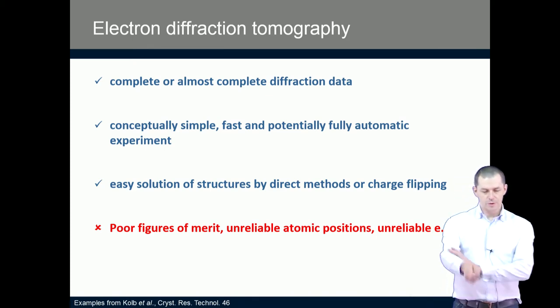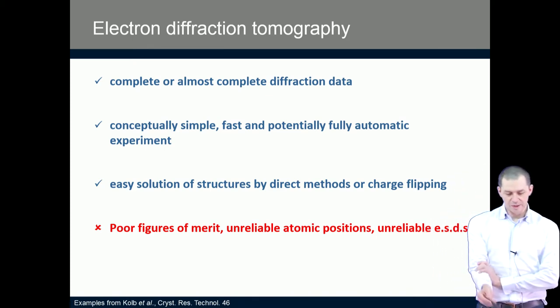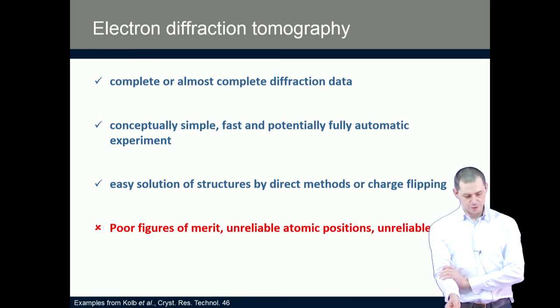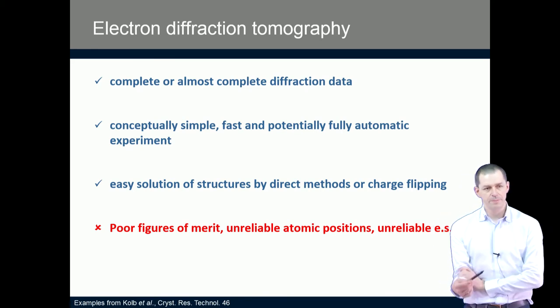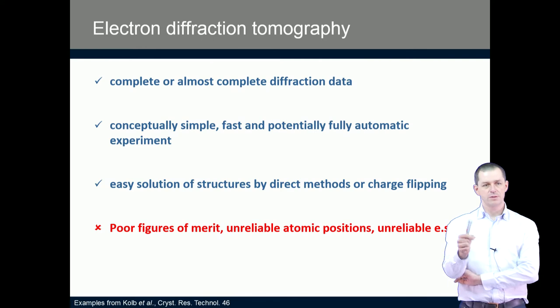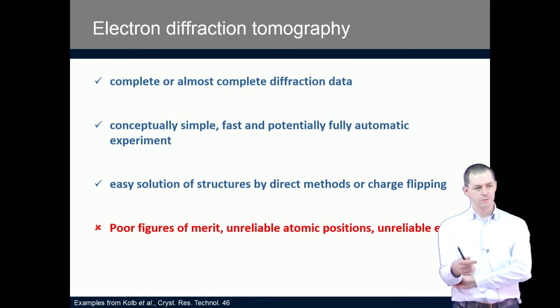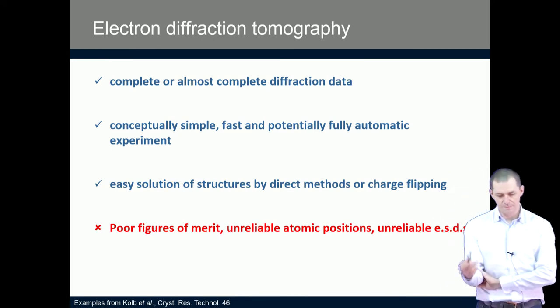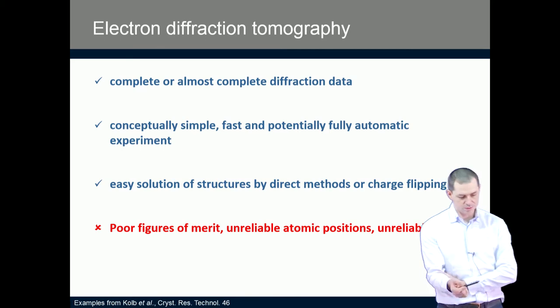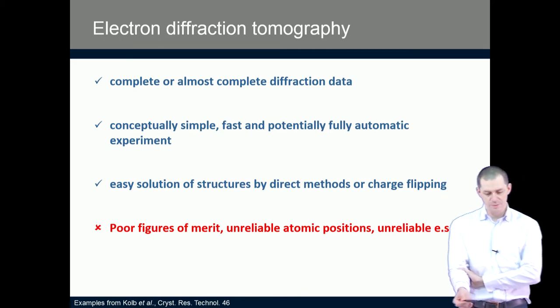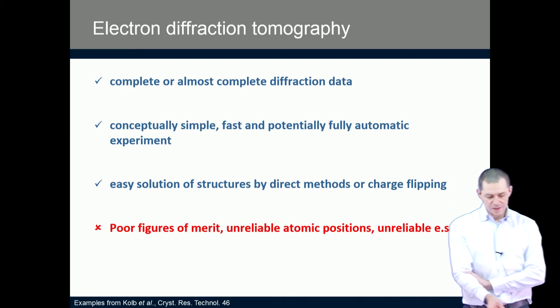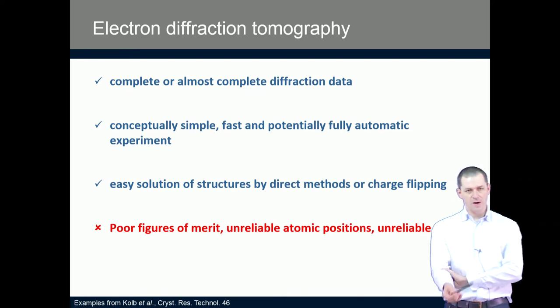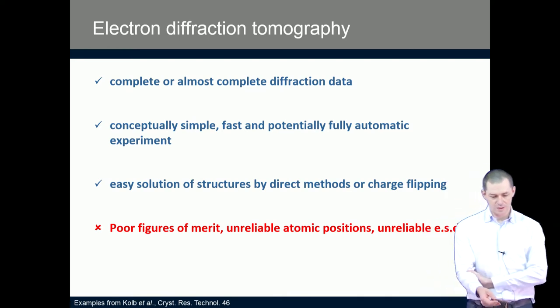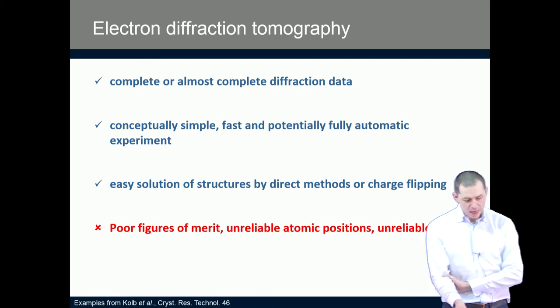So electron diffraction tomography has the advantage of providing complete or almost complete diffraction data. It's conceptually very simple. You just find the crystal and record the series of diffraction patterns without any prior orientation and so on, so it can be fully automated. There are easy solutions coming out of such data using direct methods or charge flipping.